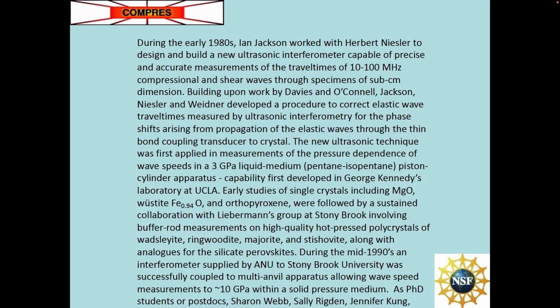And again, I apologize because my slides are out of order and all my notes are submerged, and in addition to my scratchy throat. It was really work by Jackson, Niesler and Don Widener, who developed a procedure to correct the elastic wave times measured by ultrasonic interferometry for the phase shifts arising from the propagation of these waves through the thin bond coupling to the crystal. And they applied this in a 3 GPa liquid medium apparatus of the kind that was originally developed by George Kennedy at UCLA. And then we bought the ANU interferometer and installed it at Stony Brook. And I think the next slide is going to show some of that.